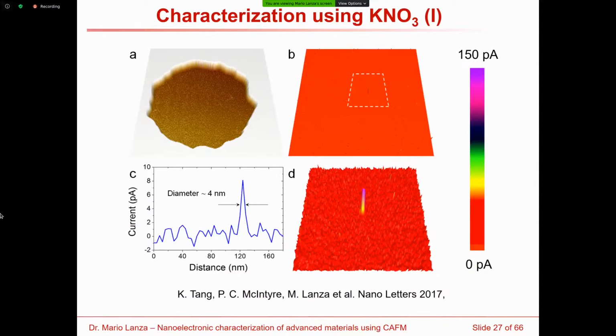But at the end, we finally found successfully that all the points that you see here, according to this scale of 150 picoamps, don't show remarkable currents except one single point, which is driving most of the current across this structure, across this dielectric in low resistance state.